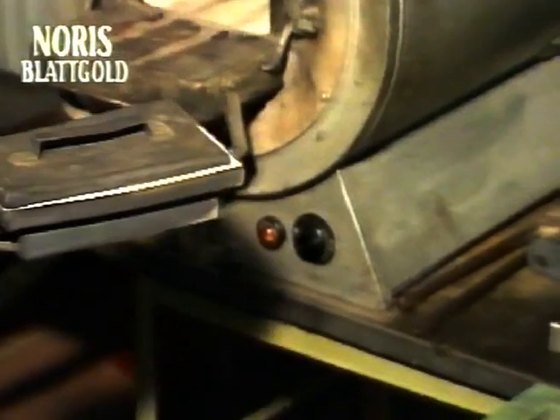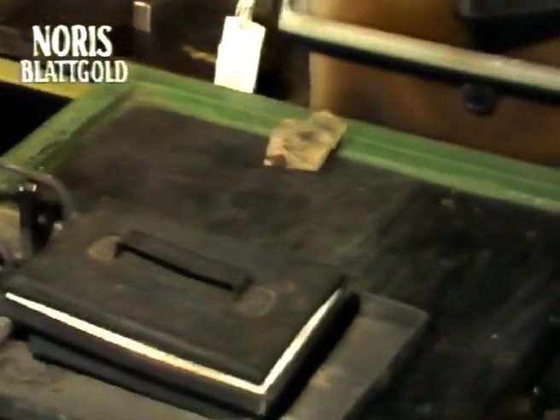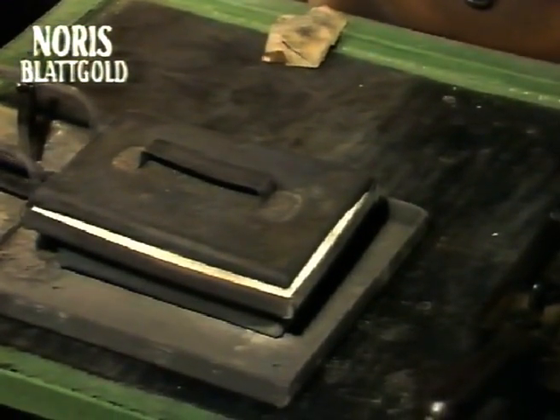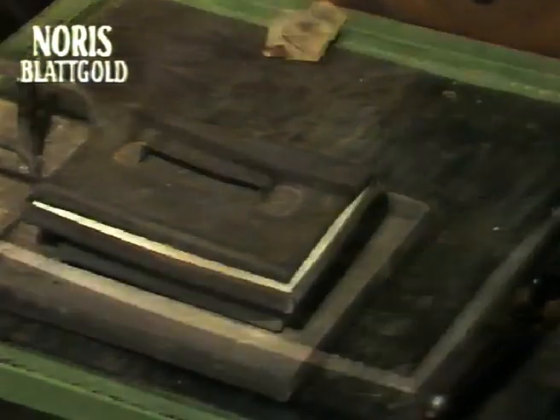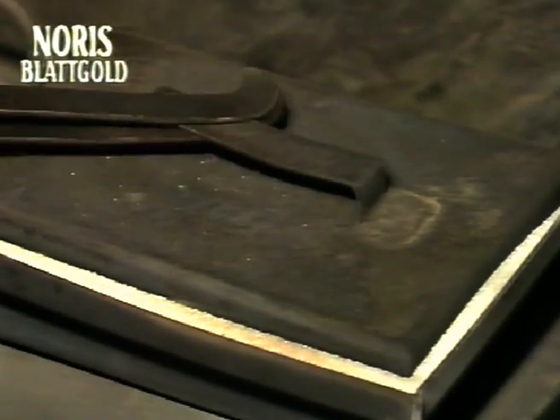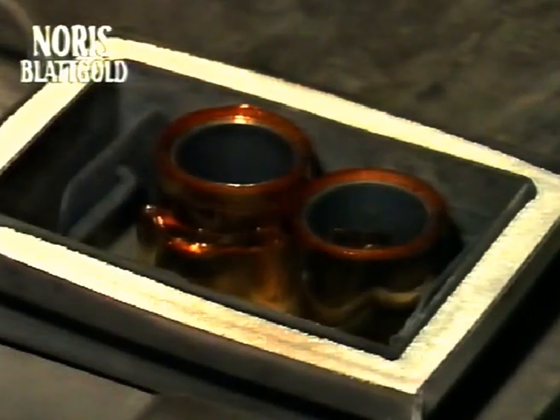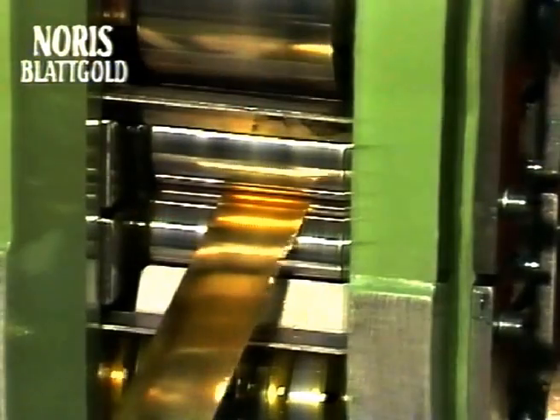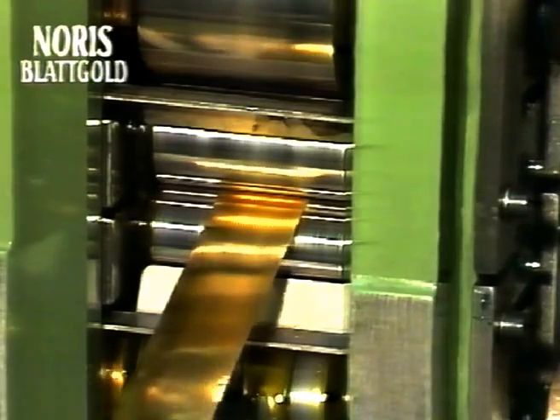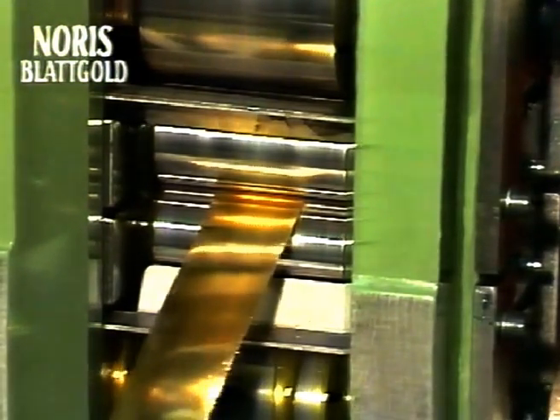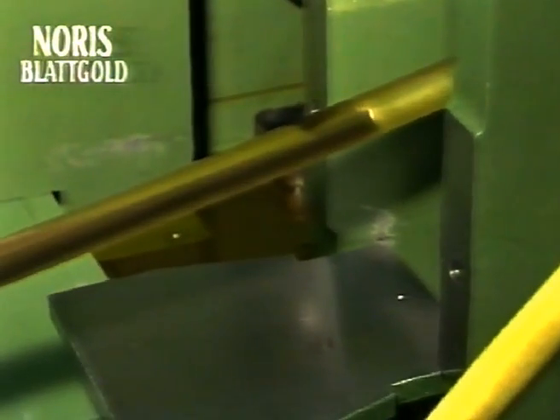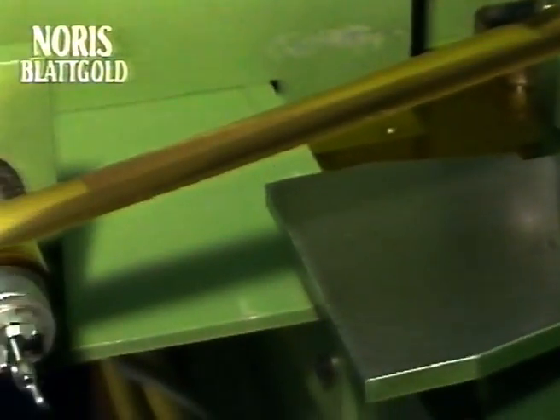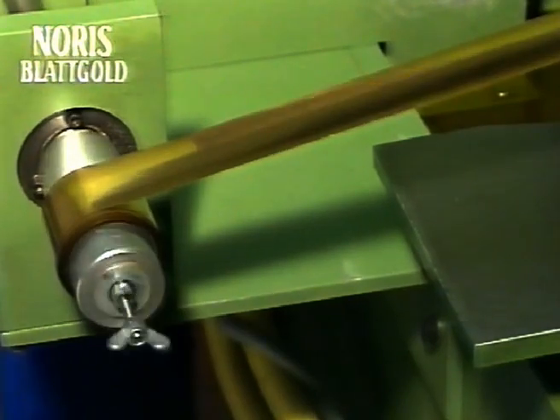The gold hardens as a result of the extreme stretching it undergoes when it is rolled. To allow for further extension, it must be soft annealed prior to the next rolling. High-precision rollers then produce a foil strip 1.6 inches wide and almost 500 feet long with a constant thickness of 7 microns. That means constant quality over the entire length.